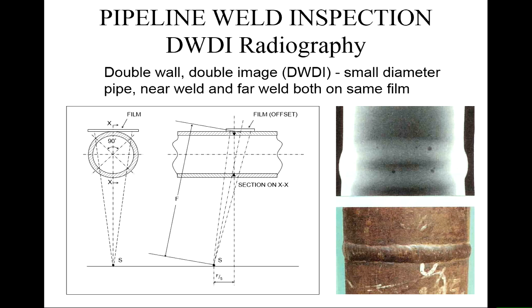So here's a weld that we're looking at, and in the double wall image, you can see two sets for the weld. One's offset from the other. So you can see here, there's one side here, and there's the other side here. And there's defects, in this case poor porosity, in both sides of the weld. So you know that that's a uniformly bad weld all the way around.